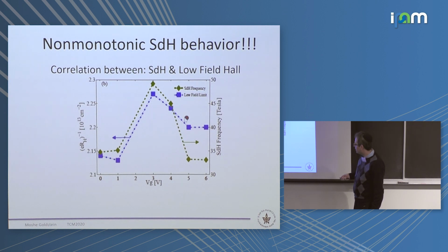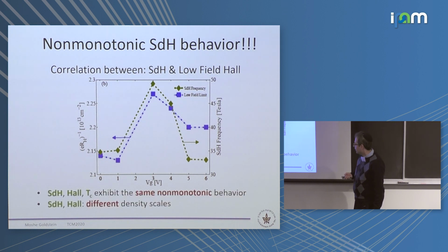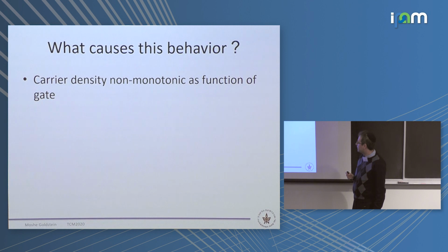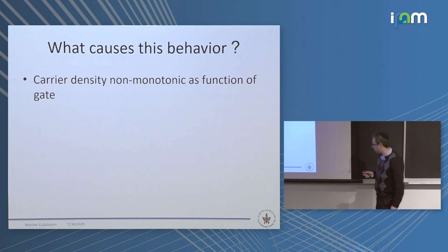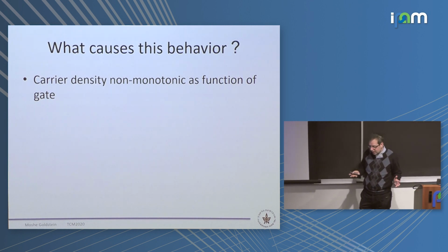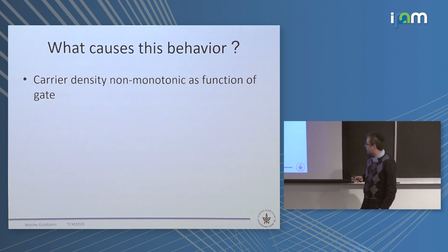And also when you translate that into density, it's again about an order of magnitude, or at least a factor of 5 smaller than what you extract from Hall, although they peak at the same point. So we need to explain that. What can cause this behavior? The first thing that comes to mind, and this is also what a referee suggested to us, is that maybe carrier density is not monotonic as function of gate, and maybe this has something to do with the nonlinear dielectric characteristics of STO at high fields.